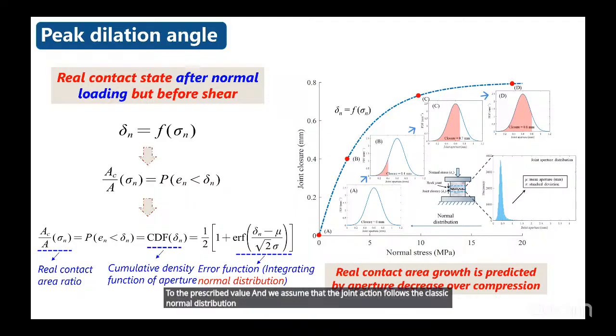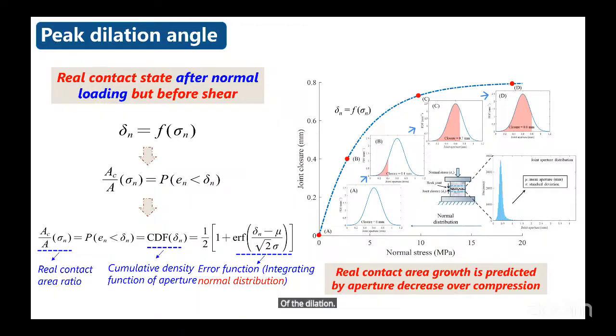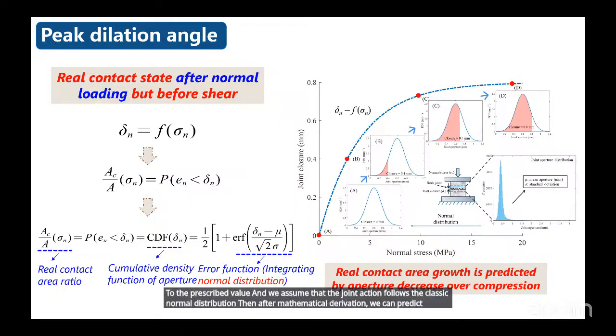Then after mathematical derivation, we can predict the real contact area ratio as the error function of the joint closure and mean aperture. Then if we have the joint closure curve from the fundamental normal deformation test, the real contact area ratio over compression is determinable.